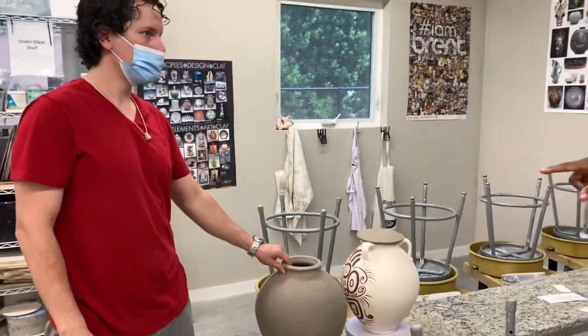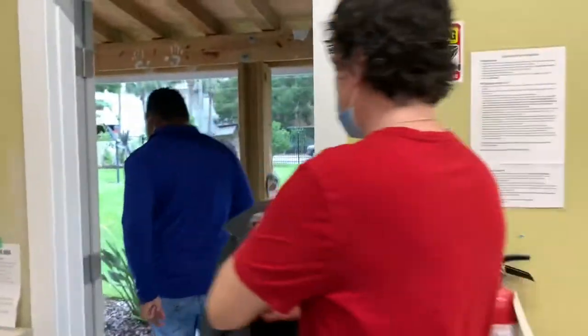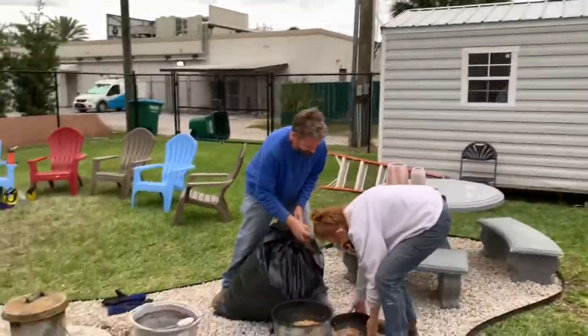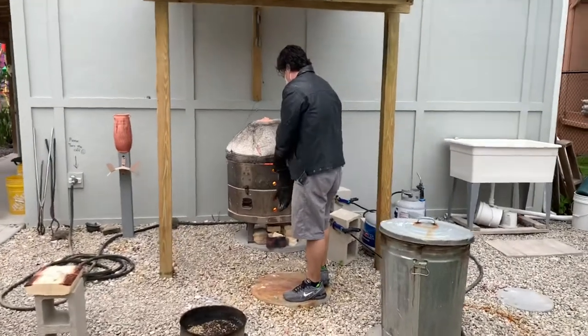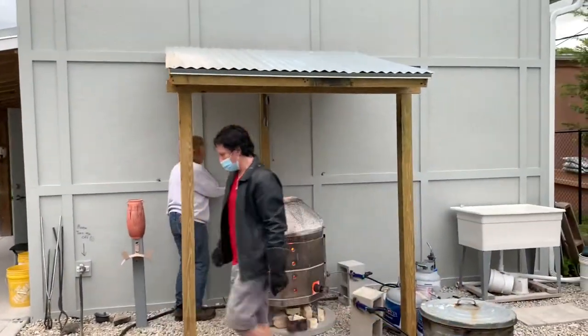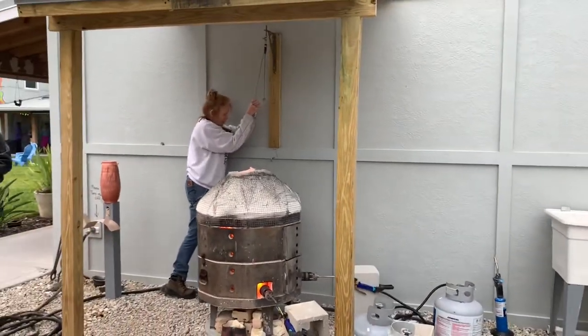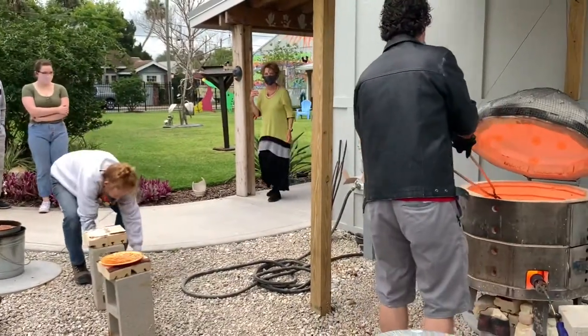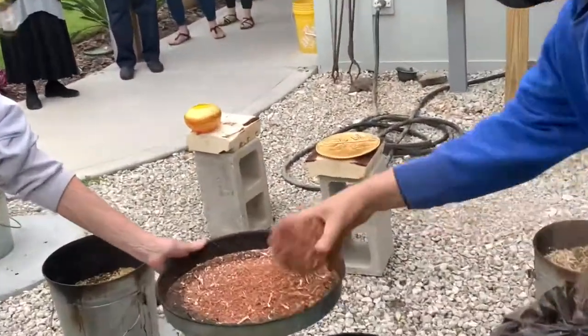About a week for larger pieces. Then you put it in the kiln. So the first step is to make the pottery — by hand or with the wheel. Second, let it dry from two days to a week. Third, put it in the hot kiln at extreme temperature for 25 minutes. Step four: using safe measures, they take big pliers, remove it from the oven, and put it in a container with combustible materials — in this case, sawdust. Once the material ignites, the containers are closed, producing an intense reduction atmosphere which affects the color in glazes. The drastic thermal shock also produces cracking. He will swing the pottery around to make it crack, which is also known as crackling. Each pottery piece is unique.